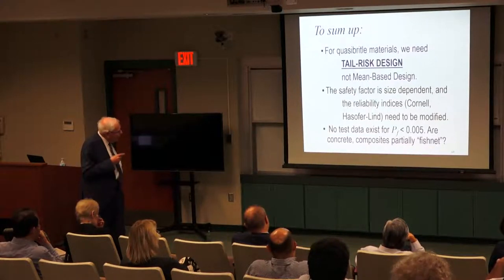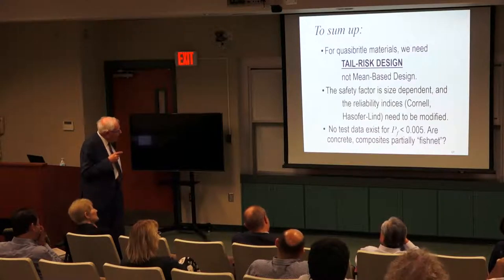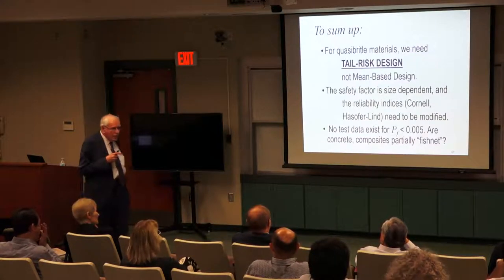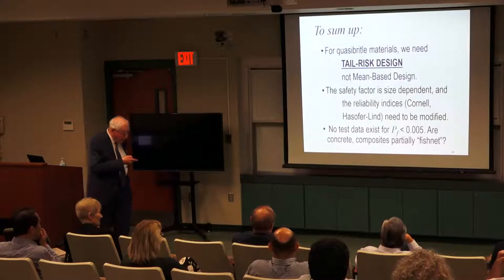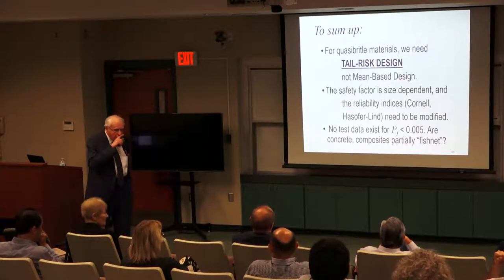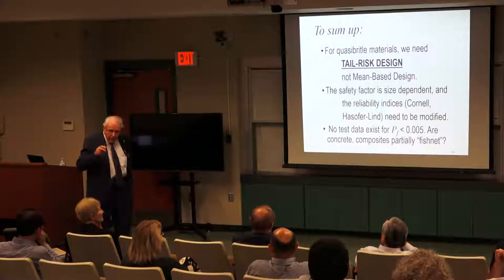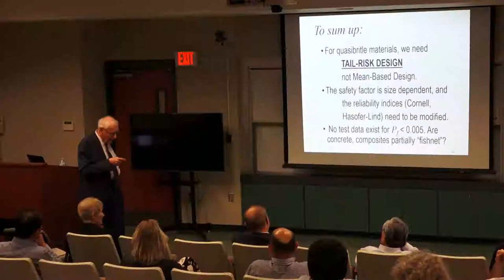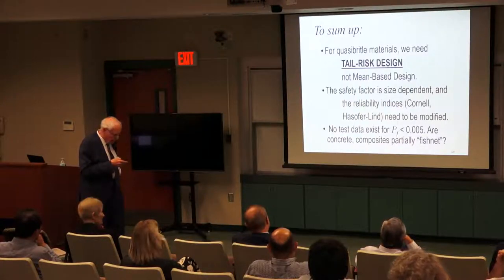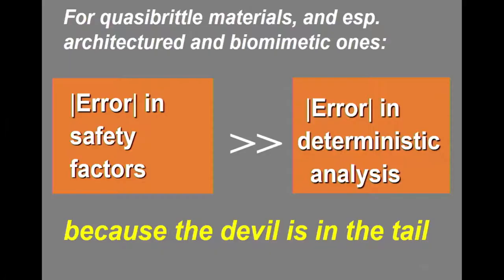And finally, I would like to point out, experimentally, in histograms, we have no data below 0.005. So you need to go 3.5 orders of magnitude down to get to 10⁻⁶. The only way to check it experimentally is to predict the size effect and then argue indirectly. And that's the only way to determine it theoretically.